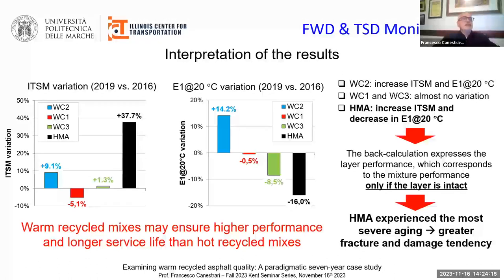To understand the meaning of these results, the variation of the indirect tensile stiffness modulus and the back calculated modulus must be analyzed together. The more interesting result is related to the hot section that exhibited an increase in the indirect tensile stiffness modulus and a decrease in the back calculated modulus. This inconsistency can be explained by considering that back calculated results are related to the layer performance. In fact, if the layer is affected by a progressive damage, the back calculation leads to decreasing back calculated modulus values over time.